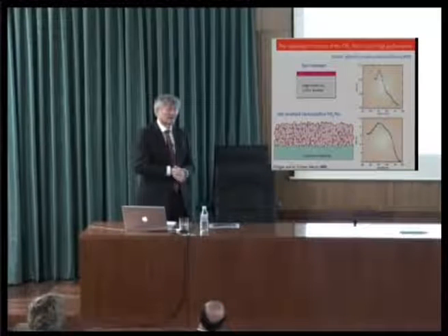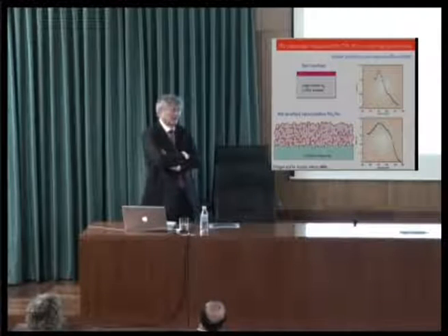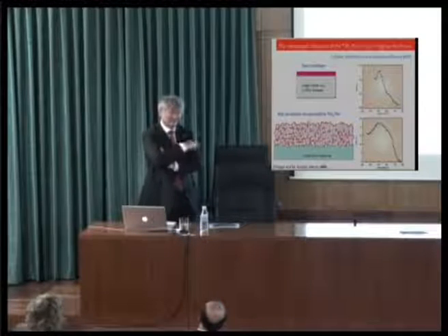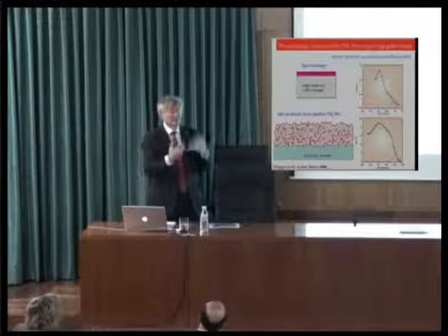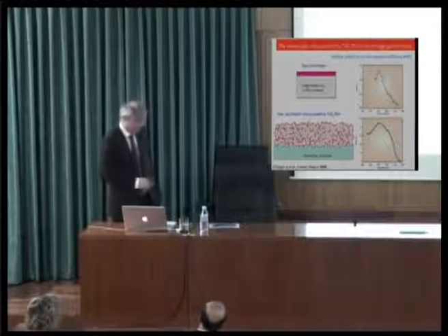Many of you are physicists. You know that for each angstrom tunneling, you have 1 over e down. Okay. So if you tunnel over 10 angstroms, you lose e to the minus 10. So that's the attenuation of the rate of electron transfer through the tunneling layer. e to the minus 10 is 10 to the minus 4. So you get 10,000 times attenuation just by having 1 nanometer of dye sitting at the interface. So that's the trick, to control the interfacial back reaction.